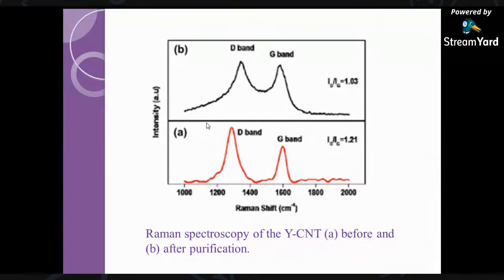So we have disordered carbon dominating this material. That's the reason why we find the ID by IG ratio greater than 1 in both cases. After purification, you can see that it has come down to a smaller value. So we can reduce the defects by a small amount through purification, but we still have carbon defects in this, which is due to the Y-shaped carbon structures.